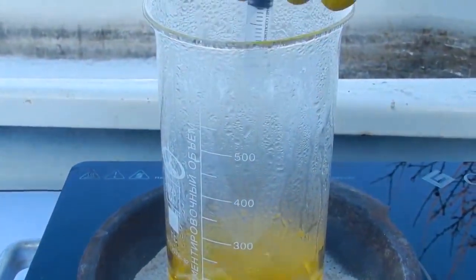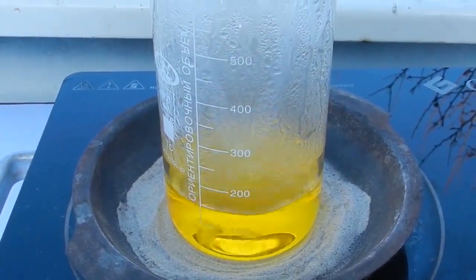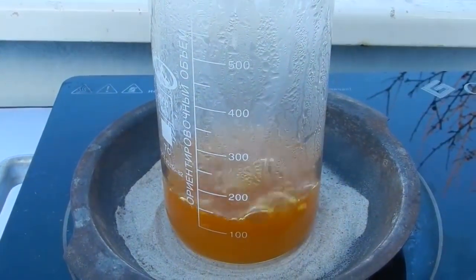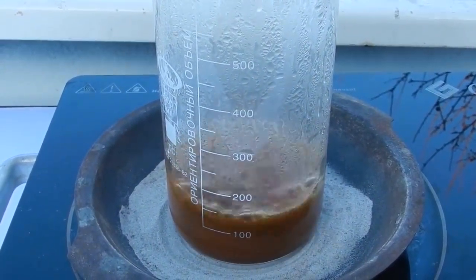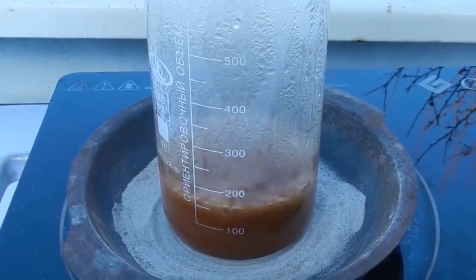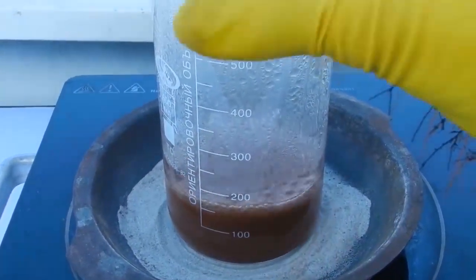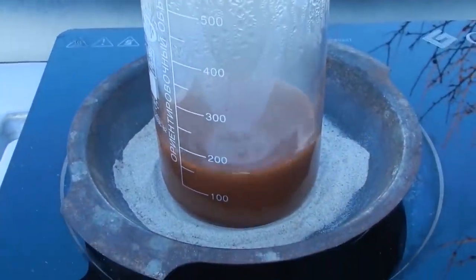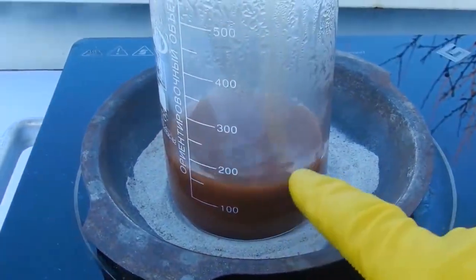Here I prepared hydrazine hydrochloride and add it drop by drop, we look. What will be our reaction now? Well, of course it's beautiful. When it boils so hard, the gold gathers very well. So, that's all. Now you need to boil the gold, everything will precipitate. By the way, already noticed, pieces gather around the edges of the glass.